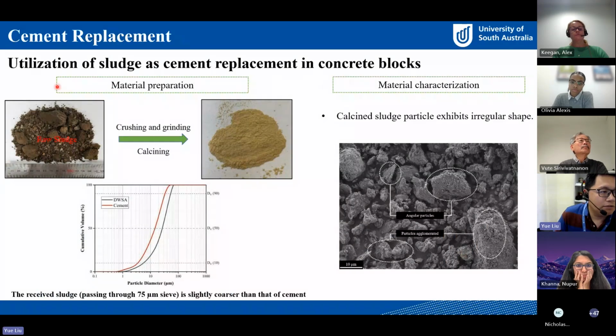For raw sludge, after crushing, grinding and calcination, we got this sludge powder we are using for cement replacement. After pre-treatment, we can see the sludge is slightly coarser than cement. And in the SEM image, we can see the sludge actually shows irregular shapes.